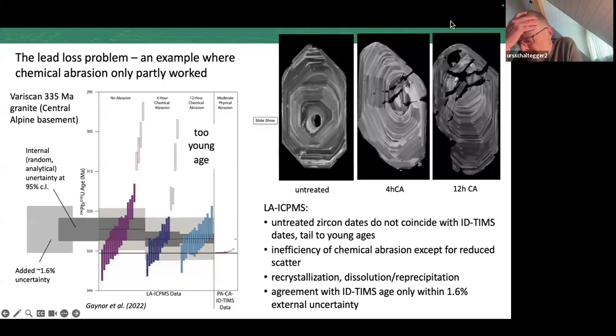No, you have to do the chemical abrasion before, because otherwise you leach the parts of the grain which are still at the first percolation point. You nevertheless start to leach these portions of the grains. And I think also there Don knows much more than me. You can actually fractionate massively uranium from lead by just leaching. I think the very first attempt they did just leach the grains and failed entirely. This was in the 90s.